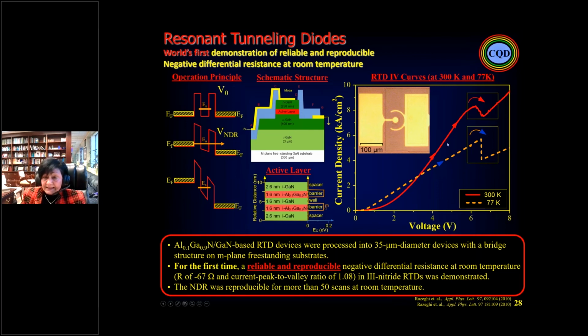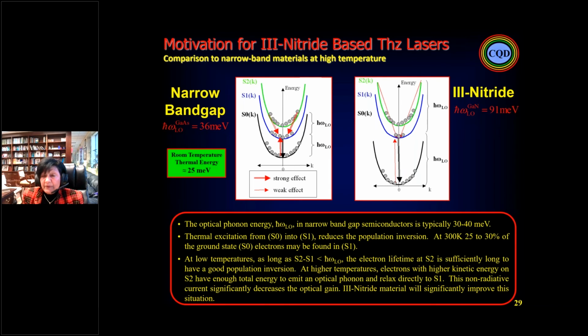But when you use that, as we can see, we can have resonance tunneling in this material, and that is important, because at the present time, for the terahertz lasers, this is very important. Unfortunately, we are using gallium arsenide or indium phosphide. The LO phonon of gallium arsenide or indium phosphide is a very low energy, 36 millielectron volts, and kT is about 25 millielectron volts. But when we go to the nitrides, gallium nitride, the LO phonon is 91 millielectron volts, much higher than kT at room temperature. So that is excellent, and important for the future study of inter-subband devices for terahertz. So that is the future.